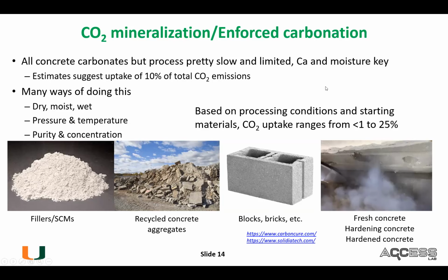And then you can actually process a lot of different materials. You can just take the fillers or SCMs - these aluminosilicates or calcium aluminosilicates - and expose them to CO2. Or you can take recycled concrete aggregate - let's say one of the buildings nearby was demolished, you make concrete out of it, and you can carbonate that. And then there's concrete products like blocks, bricks, or pavers, etc. And then, of course, you can also push CO2 into fresh concrete, hardened concrete, or hardening concrete. So all of these are possible.